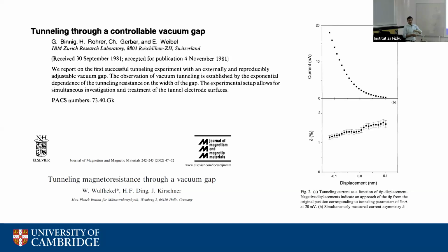I saw some nice STMs earlier in the department. In STM, what you do is use a vacuum gap to tunnel. And people have also shown spin-polarized tunneling through a vacuum gap. In this paper, they show that if you use a ferromagnetic tip, you can actually introduce spins. This is the displacement. If you change the distance, which is around 3.5 angstroms, by around 0.1 to 1 angstrom, you see an MR or spin asymmetry of around 1%. So it is in principle shown that you can use a vacuum gap to introduce spin, but this has not been shown in a device so far.